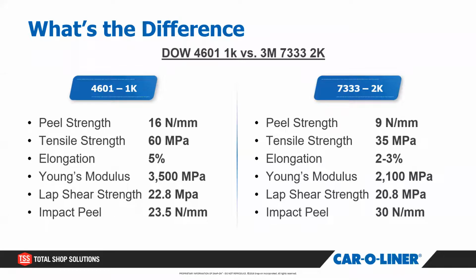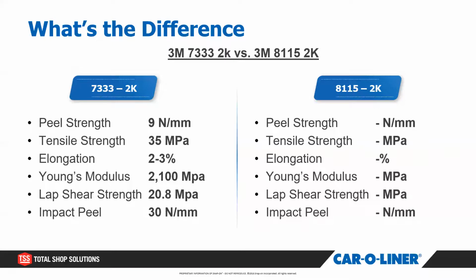Here's the difference. I compared it to the 4601 from Dow as well as 3M 7333, both very popular adhesives for different OEMs. With the 7333, the peel strength is relatively in the ballpark. The tensile strength is a little bit lower than the 4601, but still about half as much as the 1K adhesive. What's interesting here is the elongation is lower, but the modulus isn't as high. But if you look at that impact peel test, it's very, very much higher than the 1K product. All of this goes into the test.